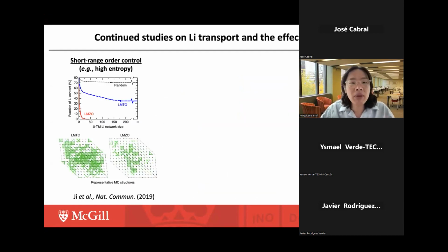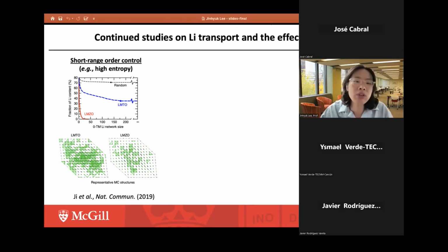Okay, but I would like to say that we need to further study the lithium diffusion mechanism in these disordered rocksalt materials, and also we have to further study the effect of the lithium-excess composition on the performance of the DRX material. In this regard, people have recently understood that in fact in the disordered rocksalt material, instead of lithium and transition metal being completely randomly distributed, there can be some kind of local short-range order, which can influence the lithium 0-TM percolation, and therefore the lithium diffusion in the structure. So these things have to be further understood.